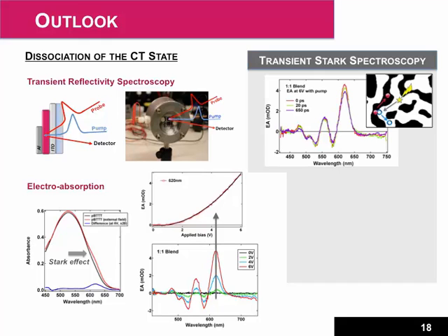And so we added additional complexity to this experiment: we measured the electroabsorption, and then we actually excited the sample with a pump. And we saw that at different times after the excitation by the pump, there is a small reduction of this electroabsorption signal. So what happens here is that when we excite with the pump, we generate charges.